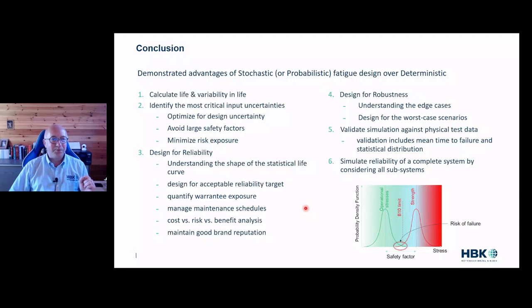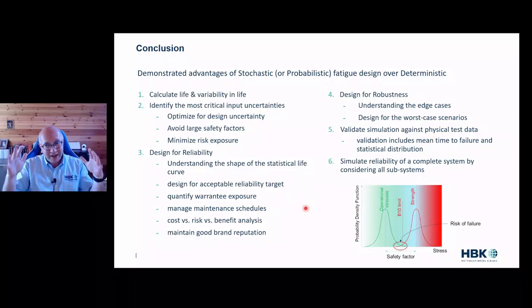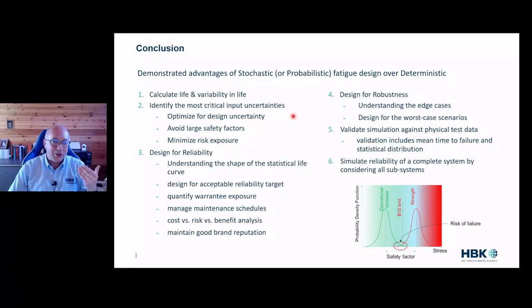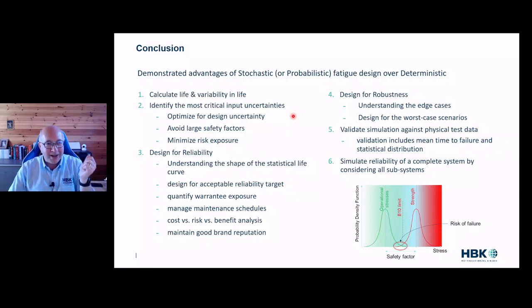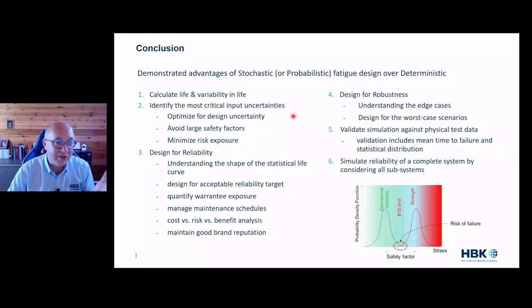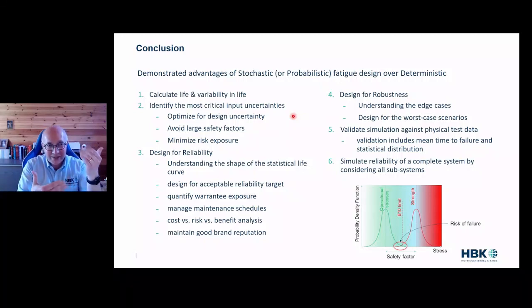And now, in conclusion, we can see that there are significant benefits in going for a stochastic or probabilistic fatigue design over deterministic, because it's all about simulating uncertainty, and there's tons of it when we deal with fatigue. Yes, we get the average life, but we also know the variability in life for each of the failure modes. It means we can start to identify the most critical inputs. So of all of the variability, which ones are affecting my design most? We can use that to optimize our design for uncertainty. That means we can avoid large safety factors, and we can minimize our risk exposure. And we can also find out whether these are aleatoric or epistemic uncertainties.